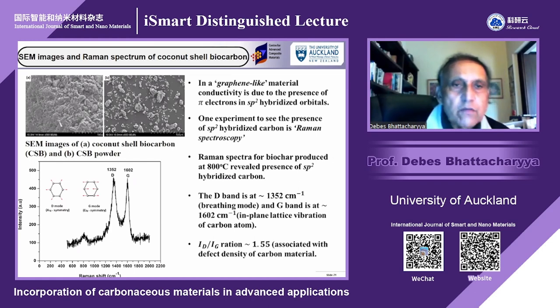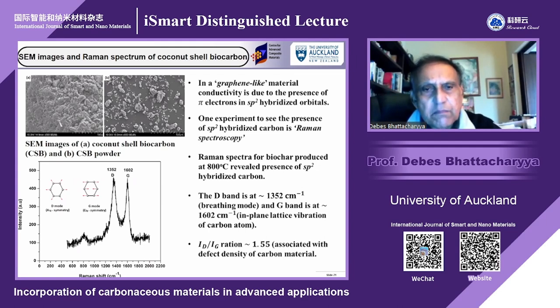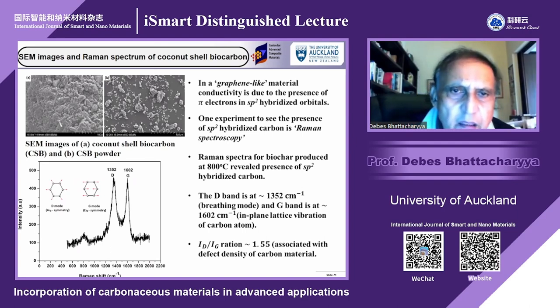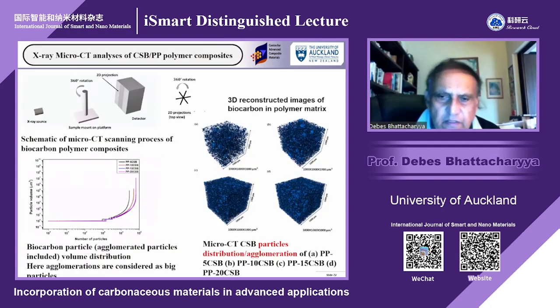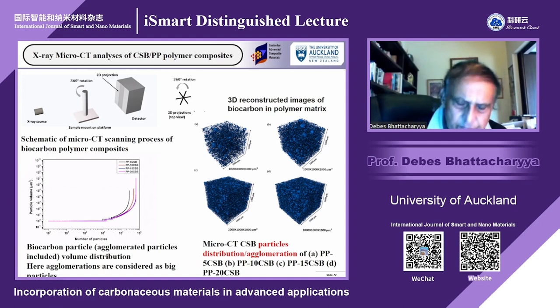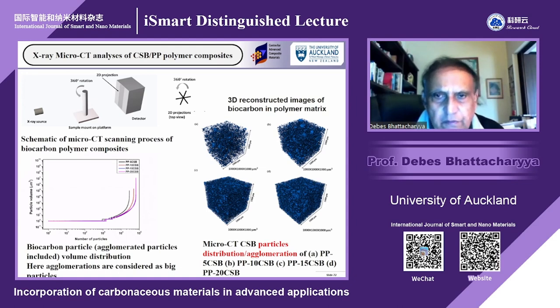On the left-hand side, we have biocarbon from coconut shell, and another is pine wood biochar, and this is actually the same one in powder form. Instead of going through the D-band and G-band, which we can explain, let us have the overall picture first. So we have taken micro-CT to show how the particles densify when you increase the percentage of this biochar, biocarbon. You can easily see how they are densifying, and that's how, after a certain percentage, you get problems rather than benefits.